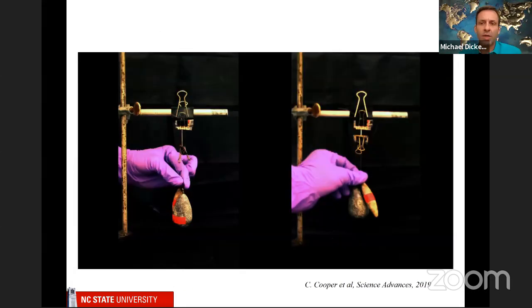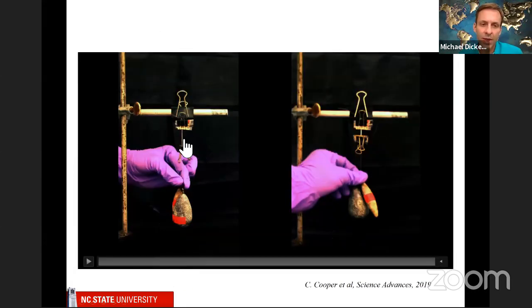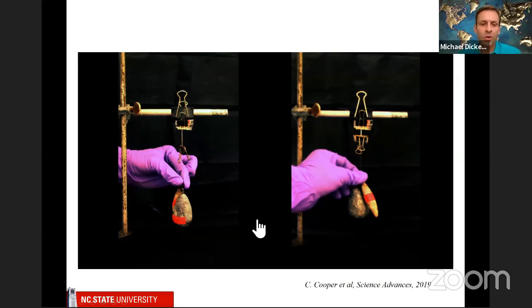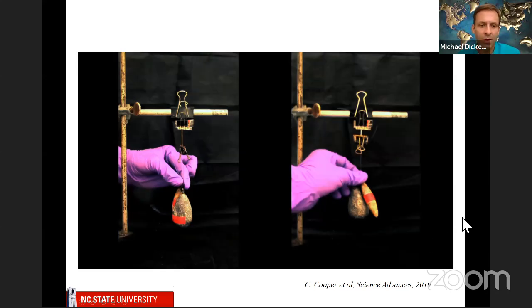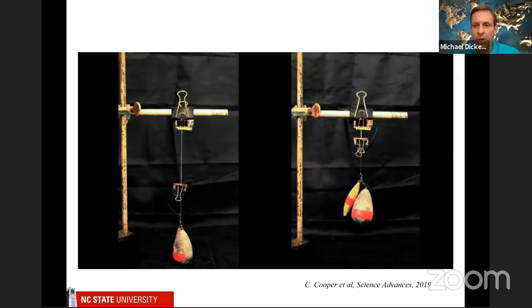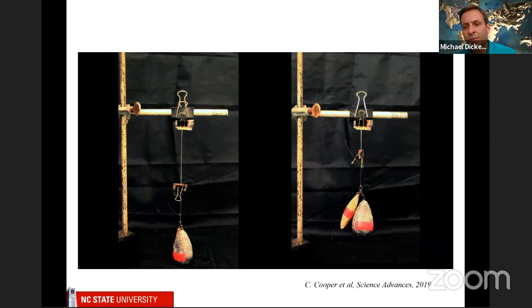Just to show you a demonstration here, on the left, this is an elastomeric fiber with liquid metal on the inside. And this is the same fiber, but with solid metal. When I hit play and we drop this little fishing weight, you'll see that the elastomer one just drops immediately. Whereas the one on the right slowly falls as it dissipates energy while elongating. First it strains the metal, but then it starts breaking the metal, until it eventually reaches the bottom.